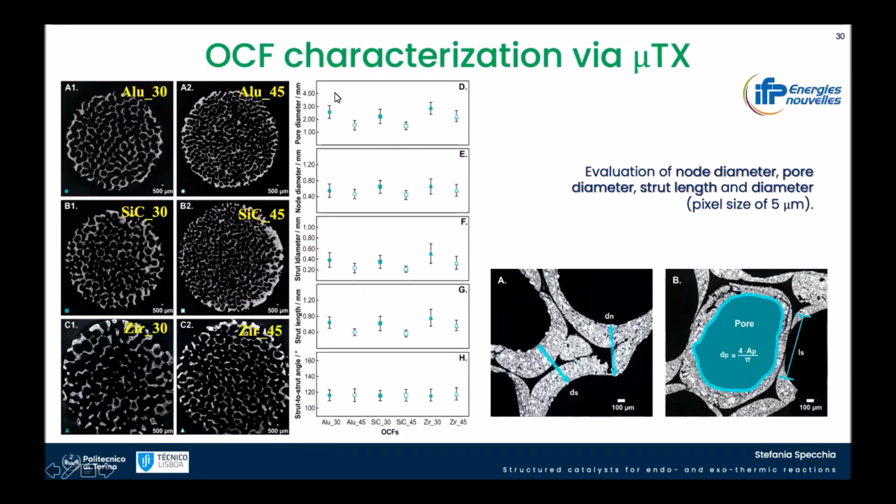And finally, just to conclude my talk, since those foams are much more difficult in terms of geometry to describe compared to monoliths, especially if we want to perform some modeling, we, together with IFP Energies nouvelles in France, performed a series of characterizations by micro-CT in order to evaluate exactly all the geometrical parameters of the foams in terms of pore diameter, strut length, diameter, and also node diameter, in order to try to recreate a 3D geometrical reconstruction of the foams that can be easily integrated in a model, and then to perform a series of modeling.